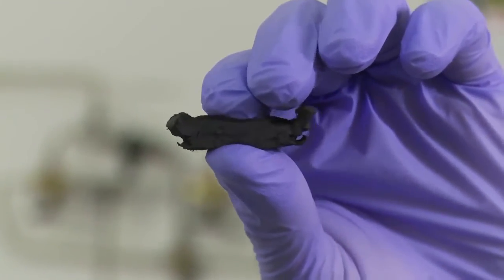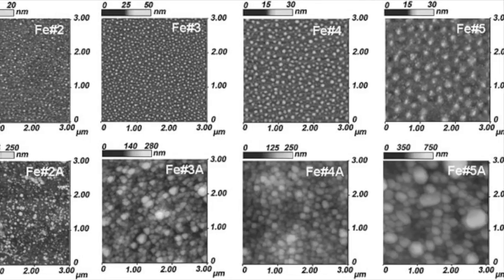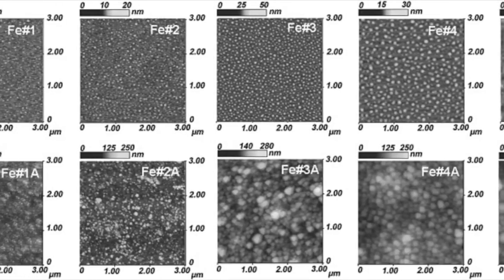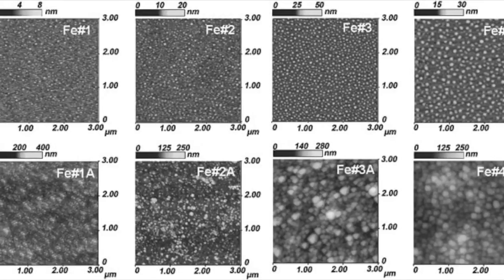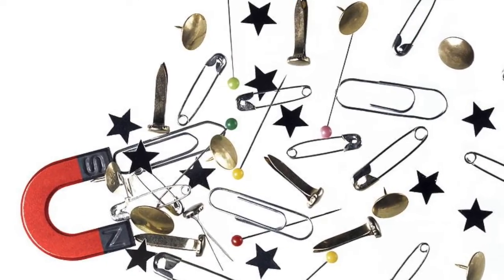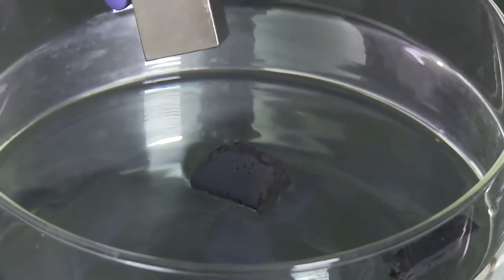A tremendous feature of these sponges is that they are reusable, potentially up to hundreds or thousands of times. Due to the iron catalyst particles used in the growth process that remain trapped in the nanotube core, carbon nanotube sponges possess ferromagnetic properties. As a result, they can be picked up by magnets, allowing for plausible collection in large waterways for reuse.